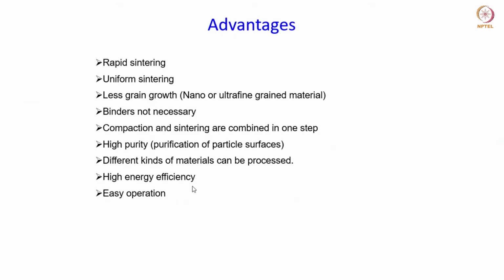Now let us also have a look at the advantages of this process. Some of them we have already talked about before. You can achieve rapid sintering, and the sintering is also uniform because of the uniform heating that takes place. Less grain growth because of the short sintering time and faster cooling, and therefore nano or ultra fine grained materials can be easily processed by the SPS technique.